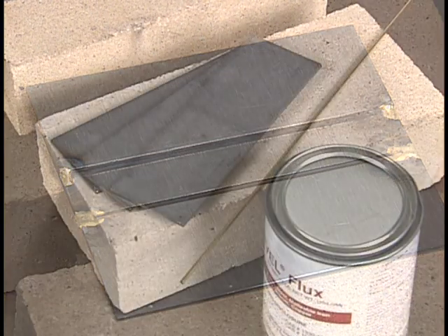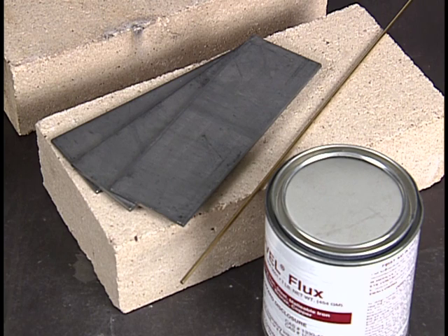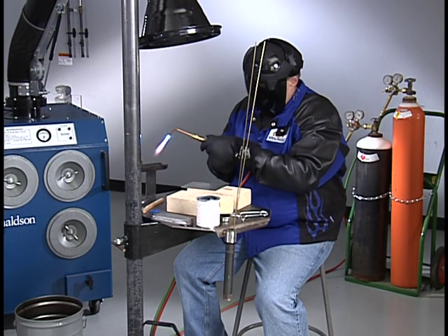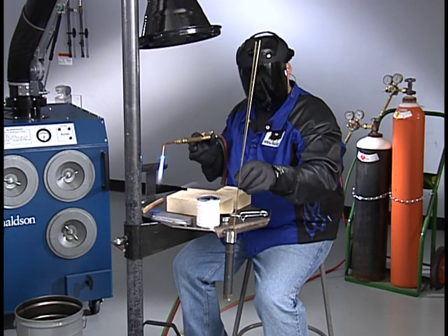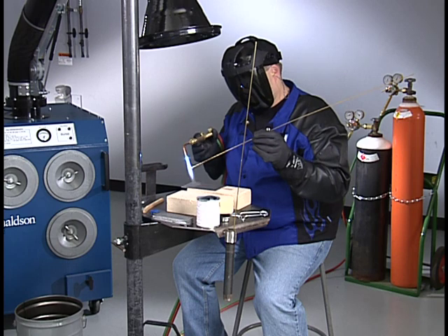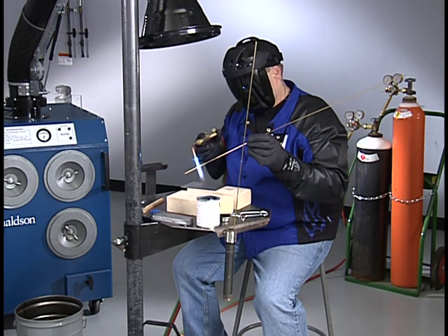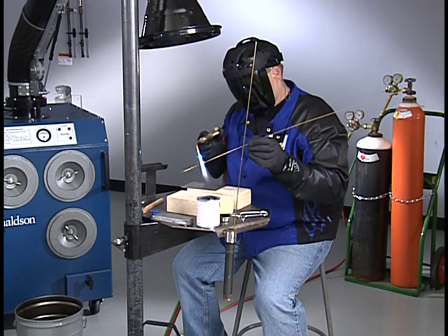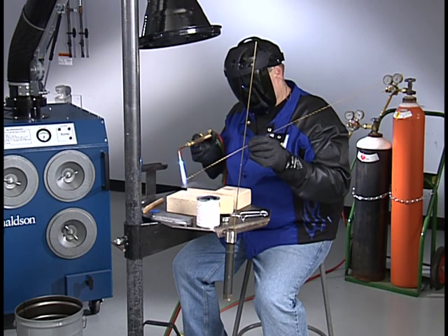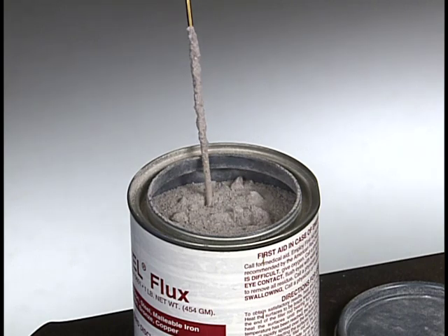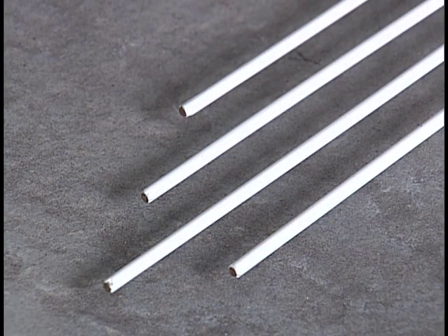To make the workpiece, take 3 pieces of 11 gauge mild steel plate, clean and deburr them as needed. For braze welding, flux is needed for preventing oxidation and for absorbing impurities. Light the torch and adjust the flame to a slightly oxidizing setting with an inner cone about 1/4 inch long. A thin, even flux coating is applied to the filler rod by heating 2 to 3 inches of the rod, then dipping it in the powdered flux. The coating should be about 1/16 of an inch thick. However, it is not necessary to dip the rod in powdered flux if you are using a pre-fluxed filler rod.